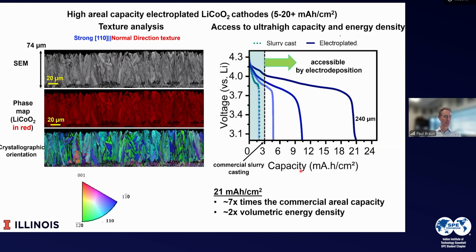For those of you that do electron microscopy, here we're using electron microscopy and specifically EBSD to determine the crystallographic orientation. By SEM, you can easily see the columnar grains. And these large columnar grains actually start at the surface as small polycrystalline grains, but then certain grains take over, and one achieves the high degree of orientation.